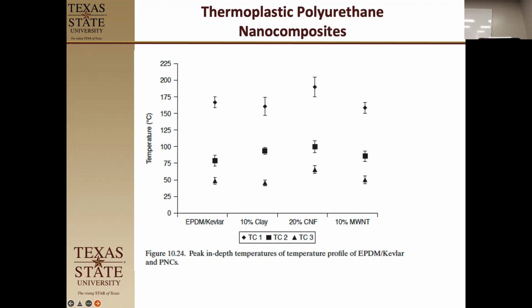So we see the one that they're trying to compete with here had, at 10 millimeters in after a 50-second burn, yeah, I think it's a 50-second burn, it was 50 degrees down here, about 85 degrees there, and about 175 degrees on the surface. But what we see in the nanocomposites is we have the same performance with clay. Carbon nanofibers actually are higher in thermal conductivity. You could have expected that, right?